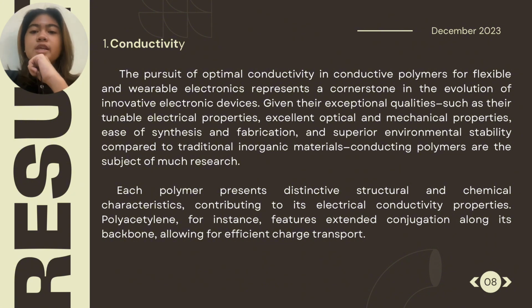Additionally, poly-3,4-ethylenedioxythiophene polystyrene sulfonate or PEDOT:PSS emerges as a highly successful conductive polymer. Its solution processability, thanks to PSS anions stabilizing the hydrophobic PEDOT chains, sets it apart. This polymer showcases exceptional traits such as high mechanical flexibility, biocompatibility, and transparency in the visible range, based on the study of He et al. in 2019.